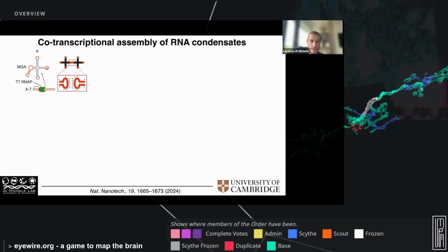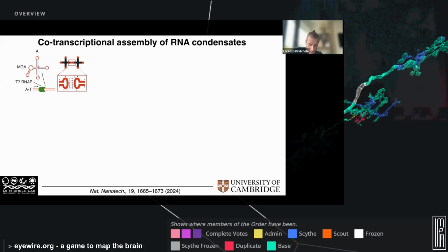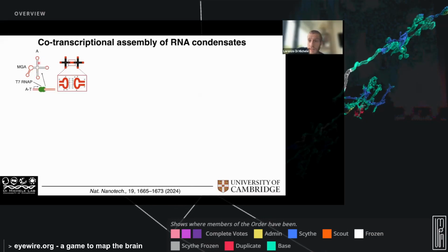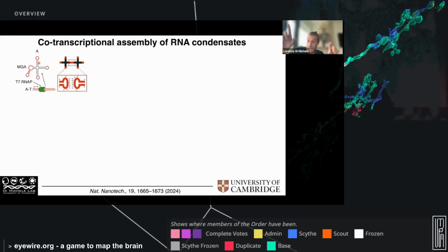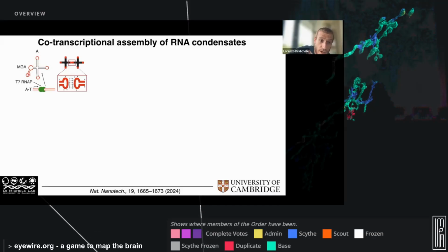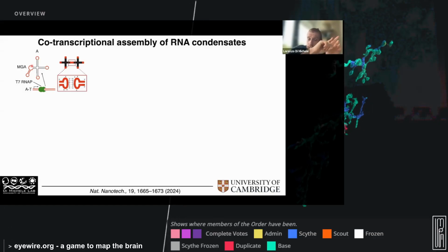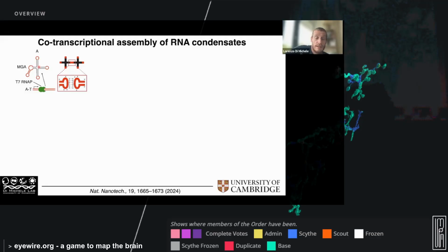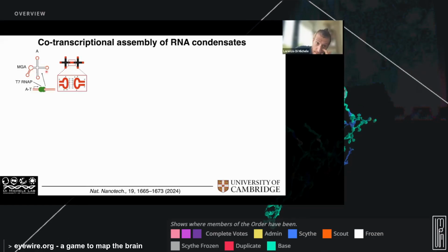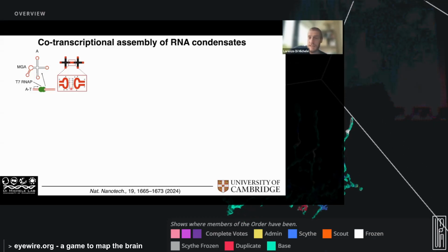So here is one such design. The key difference, really, if you compare with the DNA-based implementation, is that now this is folded from a single strand. It's not assembled out of multiple strands. You have one strand going around, forming this junction. Now, because this is a single strand, you can't have little DNA overhang or sticky ends that require multiple strands. Therefore, the way in which you induce affinity between these building blocks is by having these domains that we call kissing loops.